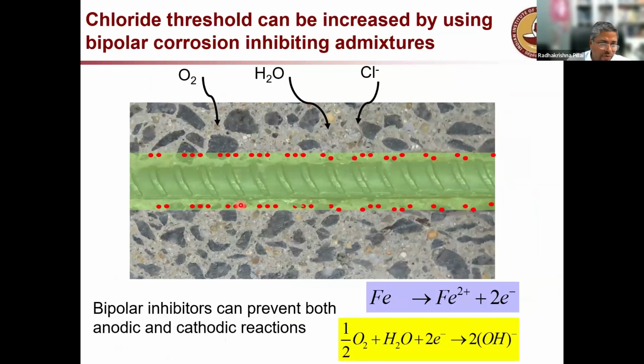Okay, somehow, one way or the other, we have to increase the chloride threshold. The other way is you reduce the speed by which chloride reaches the steel surface. Two things. One is reduce the speed by which the chloride penetrates through the concrete cover and reaches the steel surface. The other thing is increase the amount of chloride required to initiate the corrosion of the embedded steel.